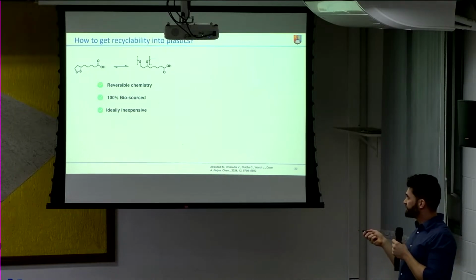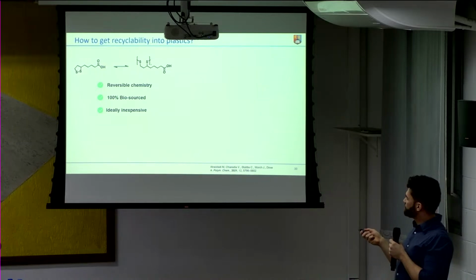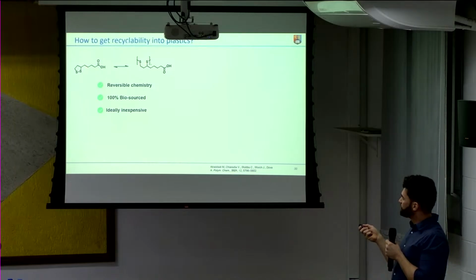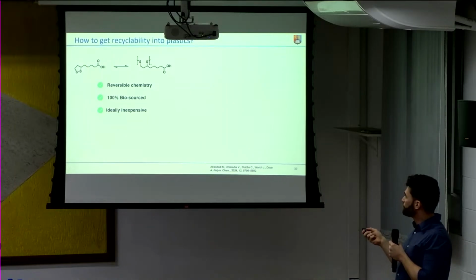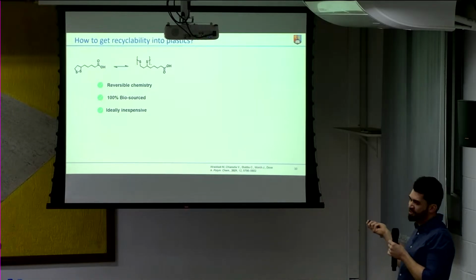So what we did was to work with disulfides. We have this bio-based molecule, lipoic acid, with a cyclic disulfide, and it can polymerize into a linear disulfide. And this is completely reversible, and it's biosourced, and it's inexpensive as well. You can buy it as a supplement.